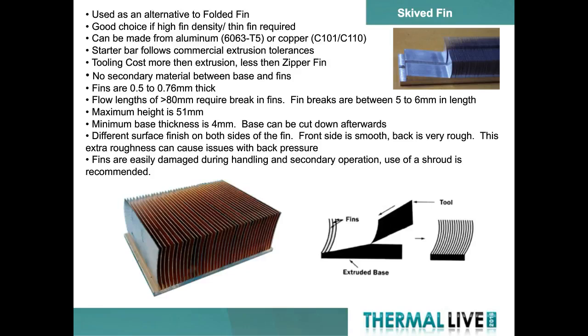The base thickness for a skived fin, due to the stress that the tool puts on the part, has to be at least 4 millimeters in thickness. We can machine it down afterwards, but if you want to try and avoid secondary operations to make the product as cheap as possible, aiming at a 4 millimeter base will give you the best success.